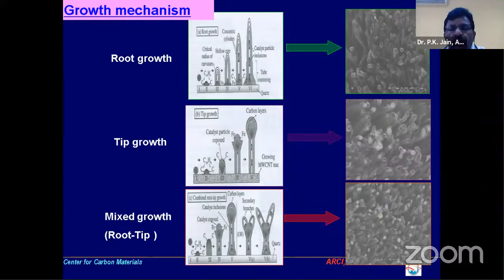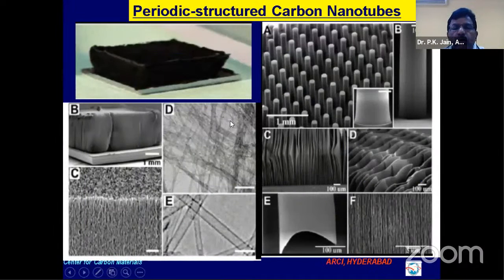As I told you, the growth mechanism of carbon nanotubes can be either root growth or tip growth. You require a catalyst. Either the catalyst will stay in the substrate, or it will go along with the nanotube, and then you can get different nanotubes out of it. You can grow nanotubes into different structures, whether it is pillars or films or pattern growth. Depending on your application, one can grow them.